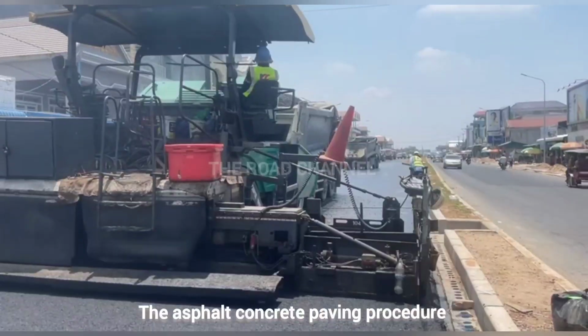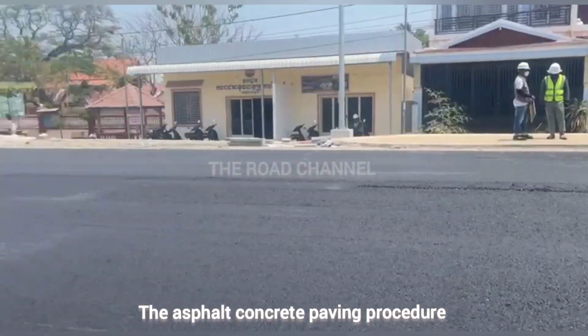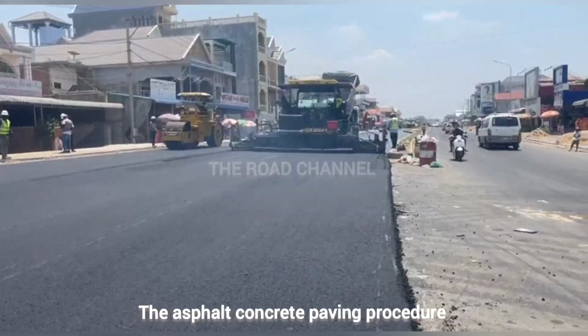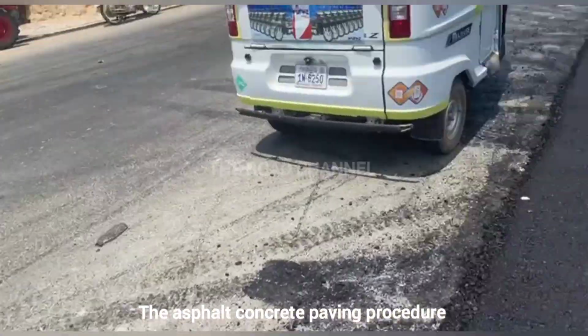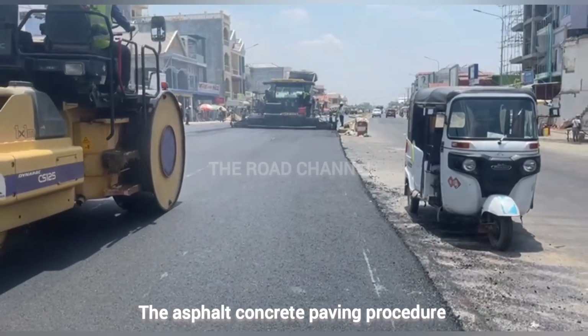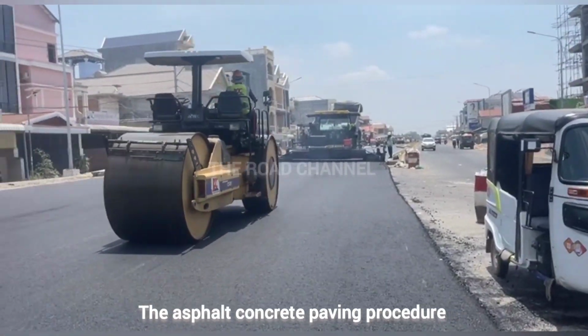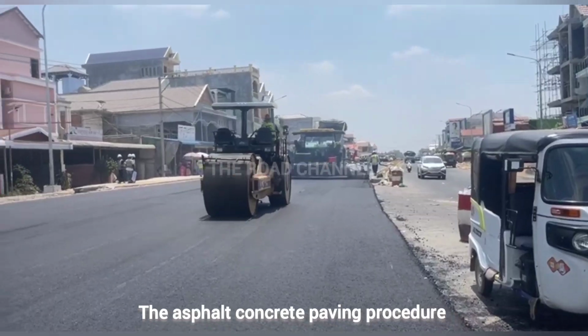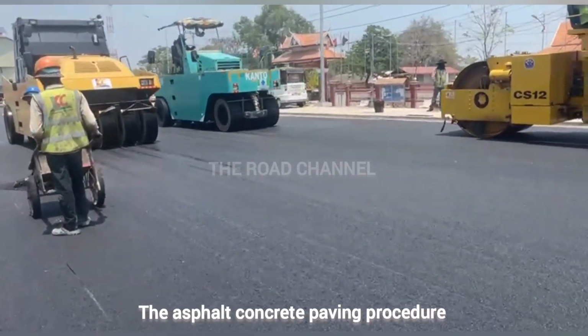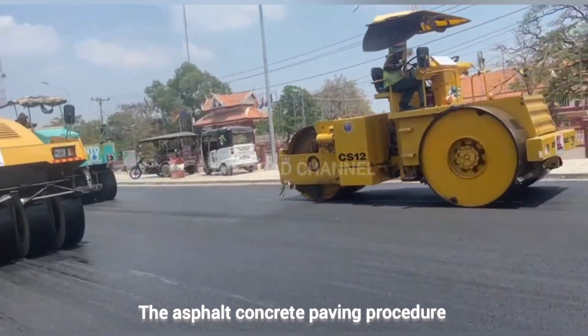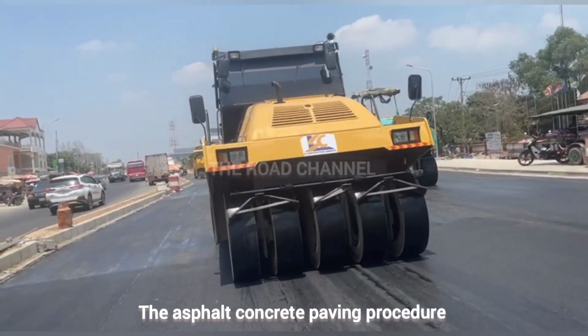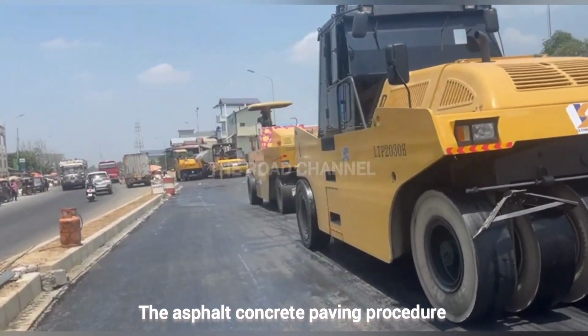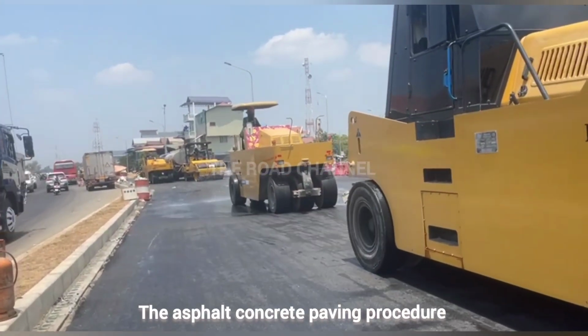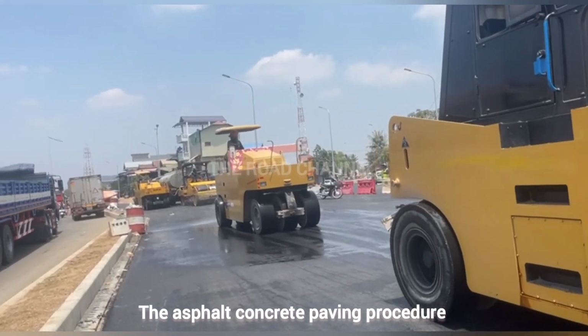4. Compaction control. Rolling pattern and equipment. Initial rolling, steel wheel roller, static or vibratory, while mix is hot, 140 to 160 degrees Celsius. Intermediate rolling, pneumatic tire roller to knead the material and reduce voids. Final rolling, steel wheel roller for surface finishing, temperature 90 to 120 degrees Celsius.